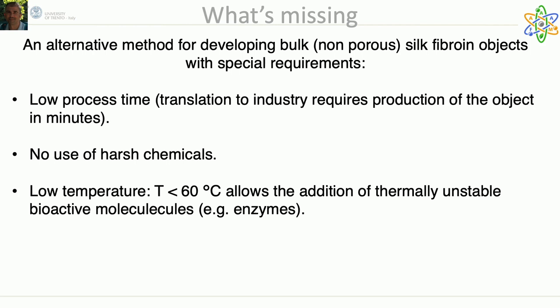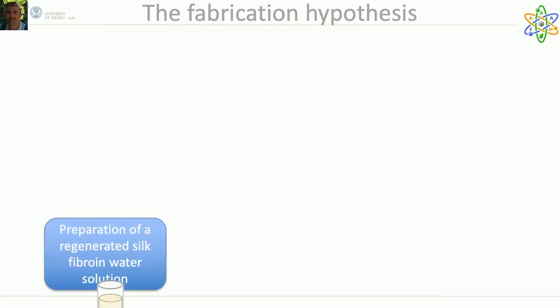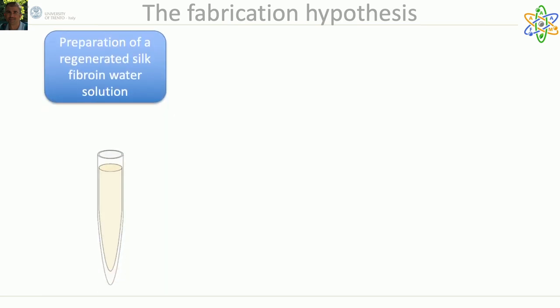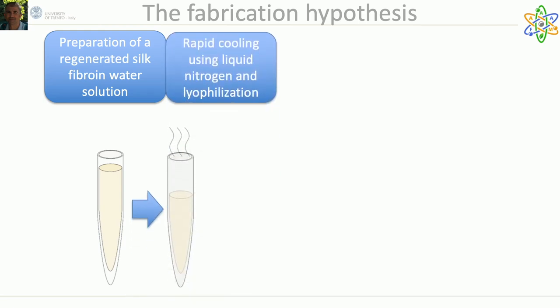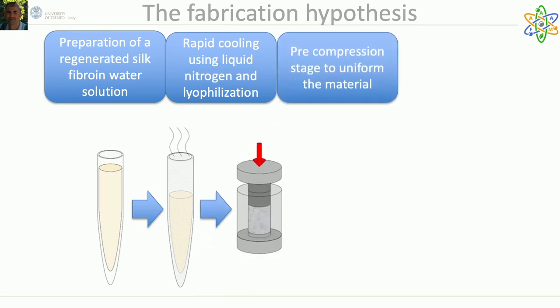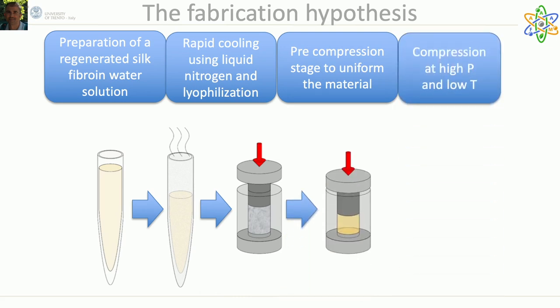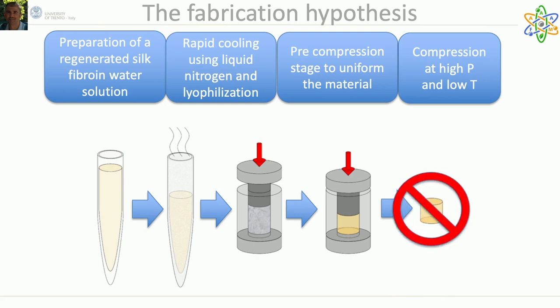A low temperature sintering of silk fibroin, which is the procedure I'm going to describe, has been reported in a paper available in Advanced Functional Materials. As a first attempt, we started from the dry fibroin obtained by lyophilizing the protein solution and just tried to simply compress it into a metal mold, hoping that a sufficient pressure could trigger the sintering. Unluckily, the procedure, unless coadjuvated by high temperatures, higher than 120 degrees Celsius, permitted us to obtain just a compressed powder instead of a sintered structure.